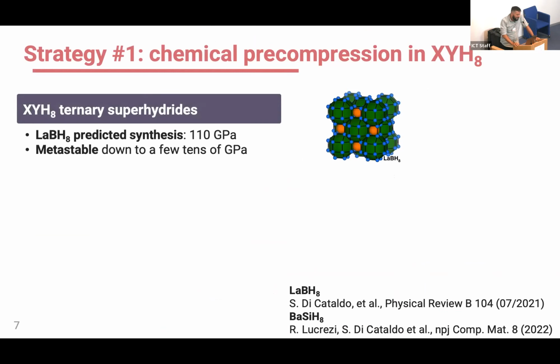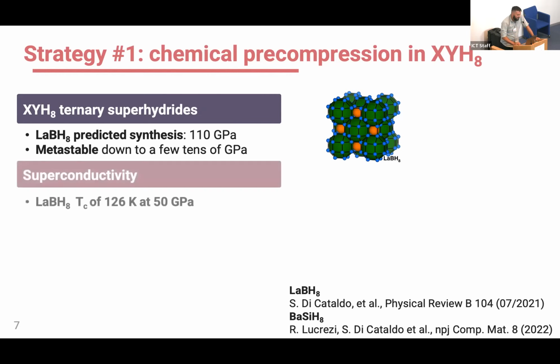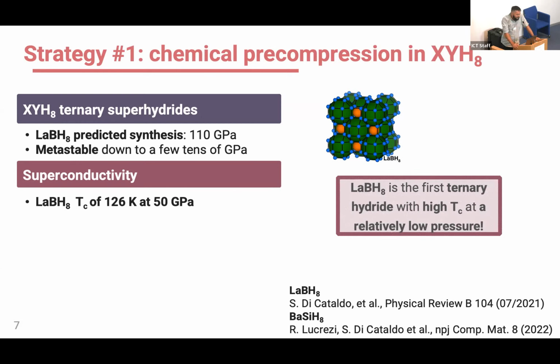Now, so these are good candidates to optimize chemical pressure. And this is basically what led us, the way in which we understood the formation of this first hydride that was presented earlier. So we predicted the formation of this lanthanum boron hydrogen 8 structure that you see here, which becomes thermodynamically stable slightly above 110 gigapascal. But then if you compute the phonons, you see that the structure remains dynamically stable down to a few tens of gigapascal. So this has a predicted critical temperature of 126 Kelvin at 50 gigapascal. So it's quite exciting. We said this is the first ternary hydride with a high TC, and now I say at a relatively low pressure, because an experimentalist would say that this is not low. It's much lower than all the other hydrides that were discovered before.